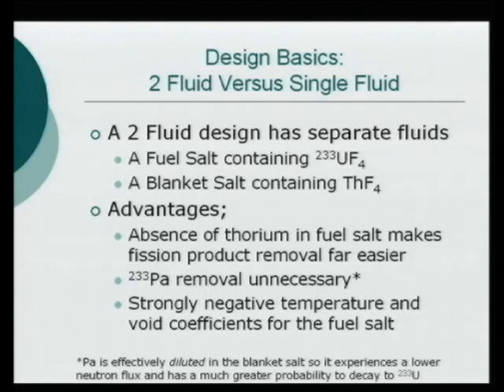Protactinium removal is not really necessary, and there's an asterisk here, I'll quickly describe that. How many neutrons you lose to protactinium is based on your power density, your neutron flux. The thorium, though, is sitting in a much lower neutron flux, or we can just have a lot more of this blanket salt, and effectively it dilutes it, so we lose a lot less, and there is really no need for any protactinium separation, which is a pretty complex thing to do. It has a very strongly negative temperature and void coefficient for the fuel salt, which is also very good.